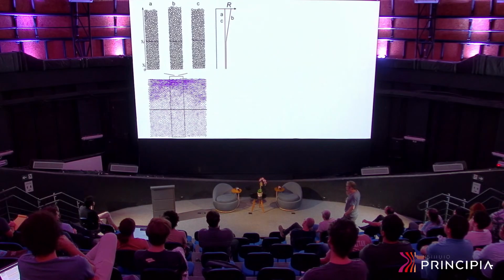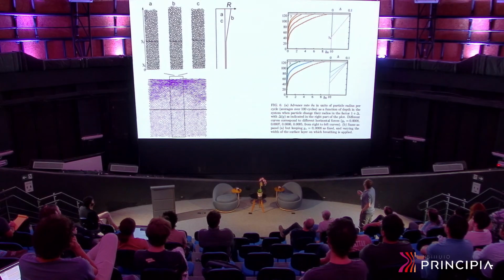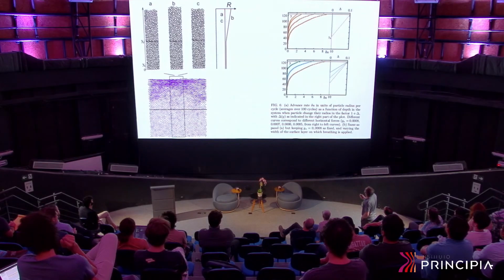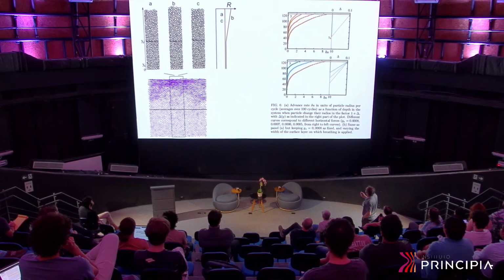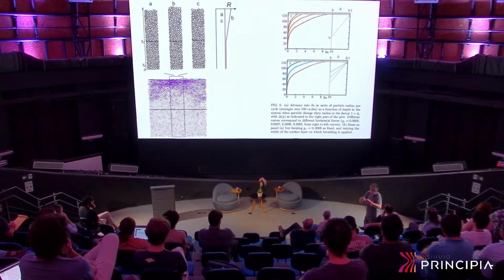So doing some statistics on this kind of simulation, we can construct curves that show the profile of movement of the particle. This is in units of the average radius of the particle: how much a particle at the surface has moved after one cycle, how much a particle at a given depth has moved after one cycle. Very quickly, is this 2D or 3D? 2D, yes. And what interactions do you have? Just excluded volume. Okay.